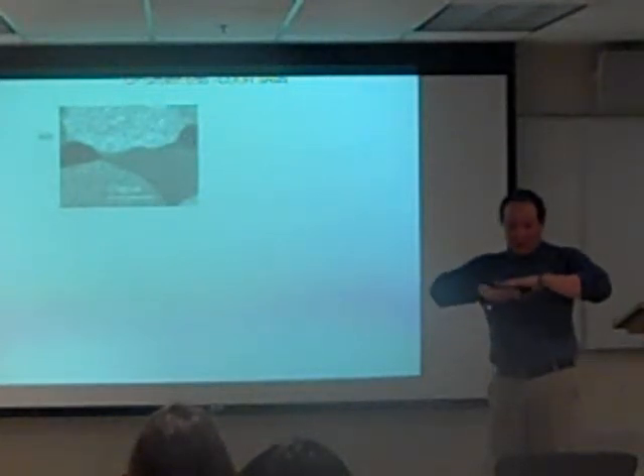However, even for a short period of time, we really don't see any crystallites. But then again, we're looking at a very small amount of material, let's say 50 to 80 angstroms thick. So we need to put it in the solution for longer periods.